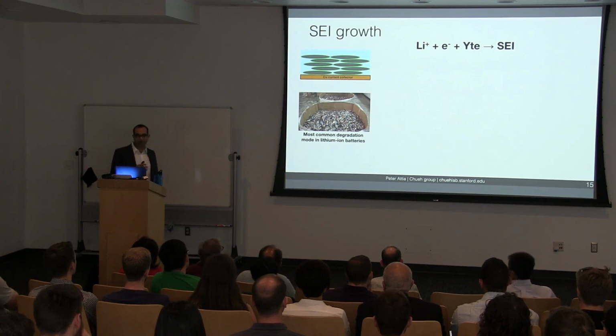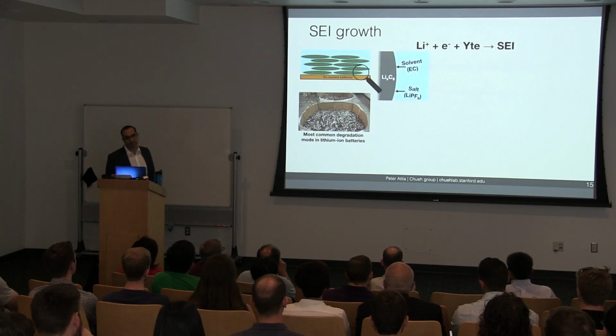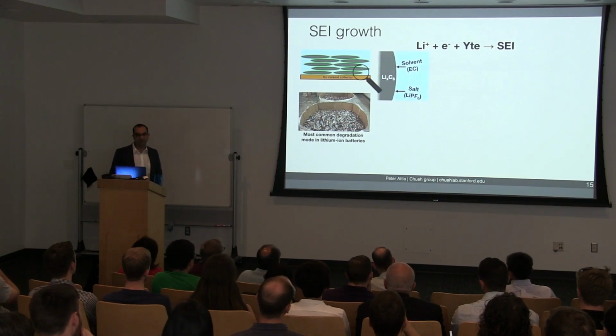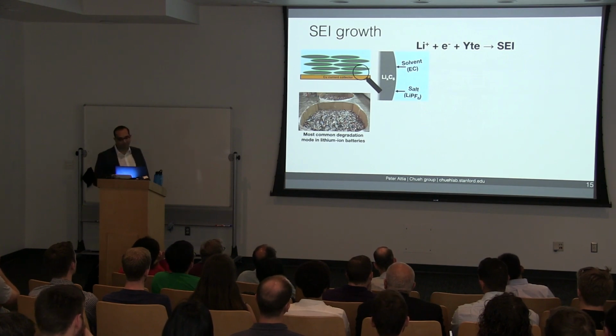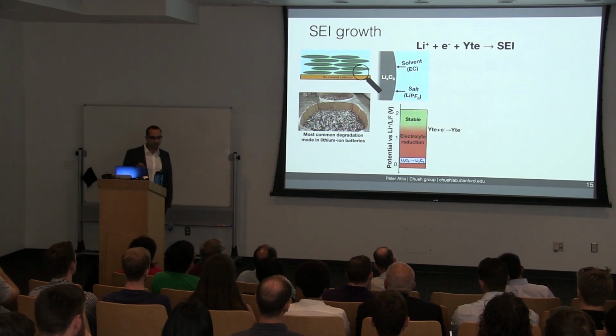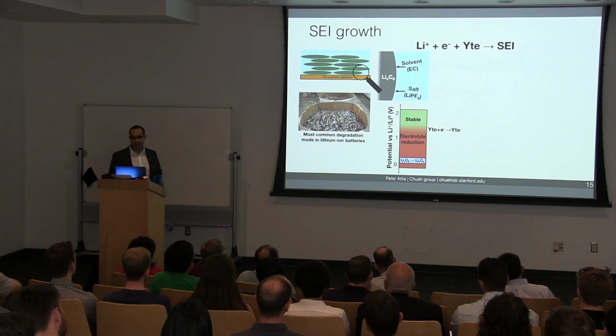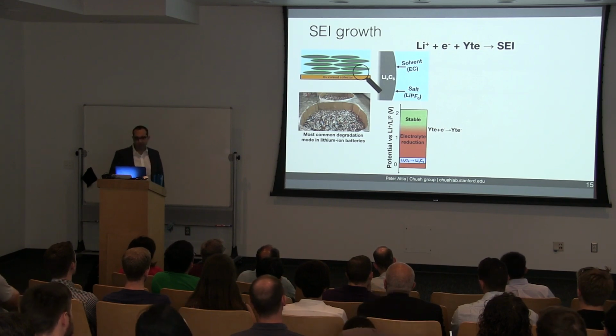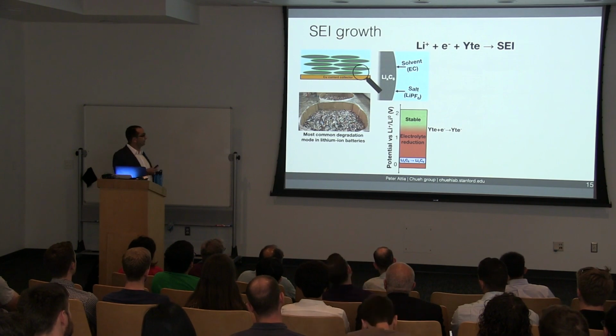SEI growth is probably the single most common lithium-ion battery degradation mode. I think it's safe to say that it's the biggest reason why your phone battery dies every 2 years. If we look at the surface of a single graphite particle, we have lithium, graphite, and electrolyte. Some of these electrolyte components include things like EC and LiPF6. Just like before, there is a thermodynamic driving force for the lithium and graphite to react with the electrolyte. It's a spontaneous reaction. These SEI growth reactions consume lithium, which reduces the overall capacity of the battery.